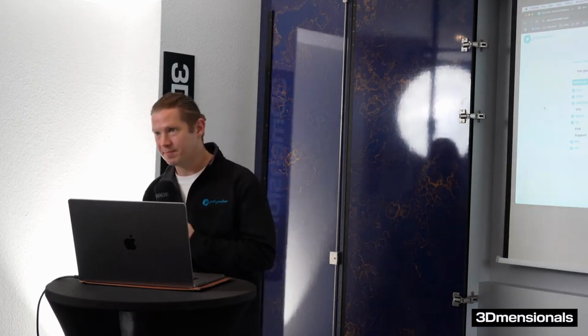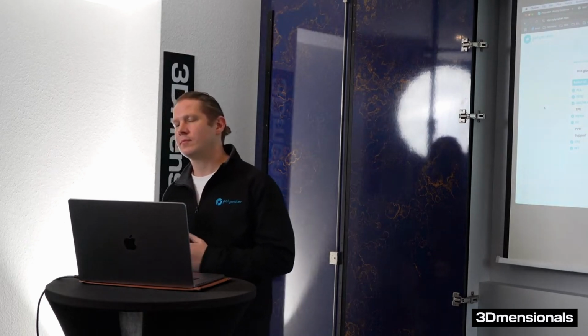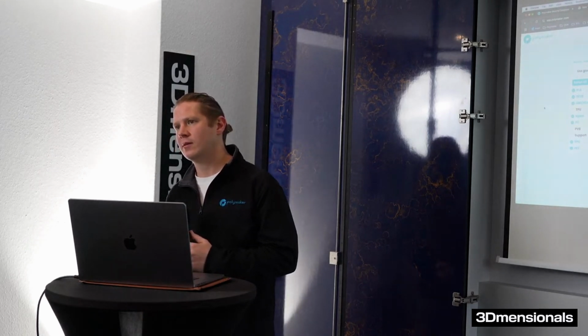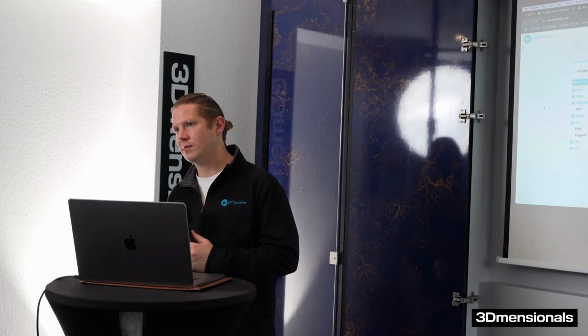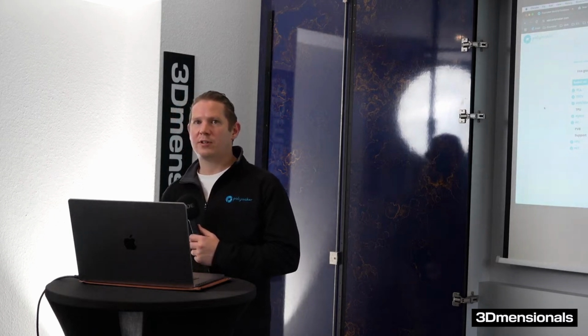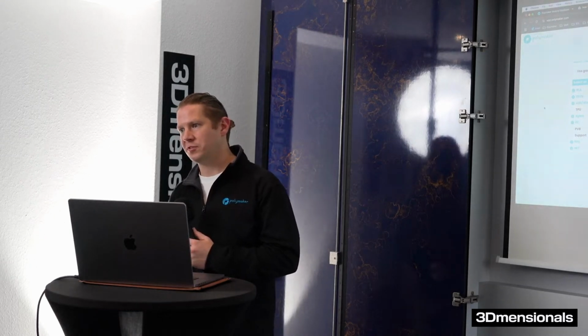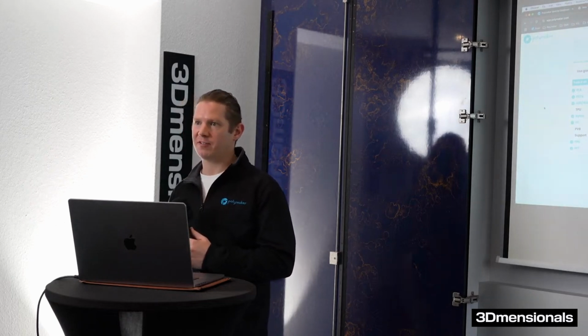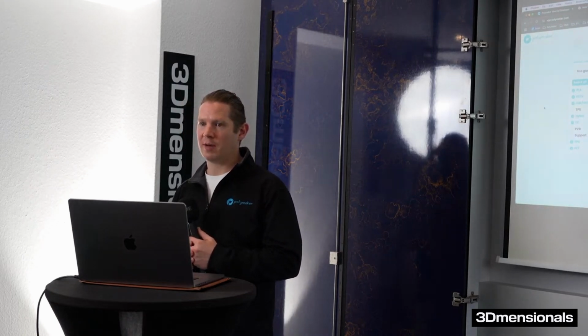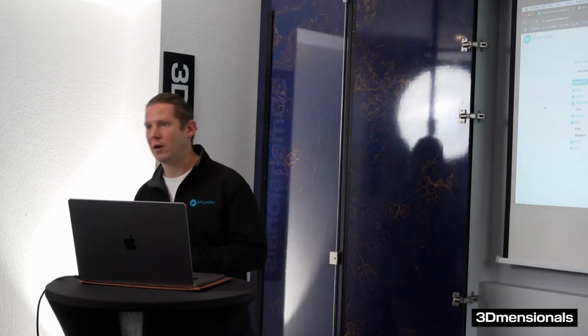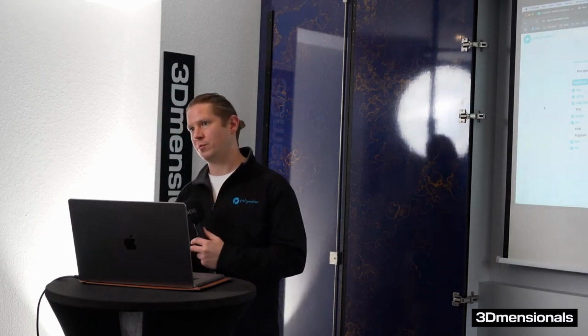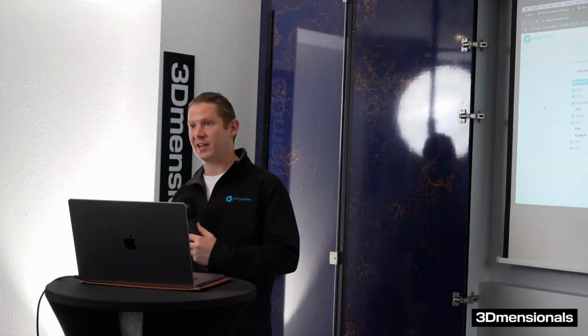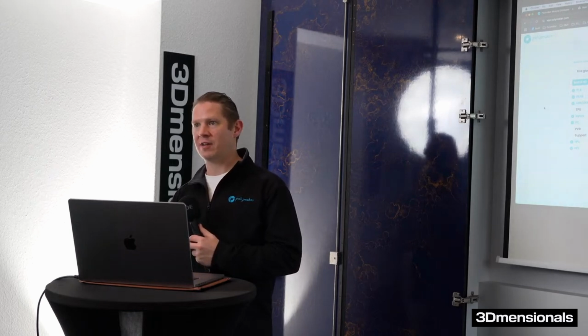I have one question. Do you have any experience about aging of your material? I have printed a couple of technical devices which are now 3 years old, standing in a normal room. Do you know how the aging and moisture is about that? Do they get weaker over time, or is it constant in normal conditions? In terms of the moisture, once you're at equilibrium, it's not changing after. That happens over about a month. With the nylon, for example, it will become slightly more flexible and slightly less stiff. But after that, it's very stable.